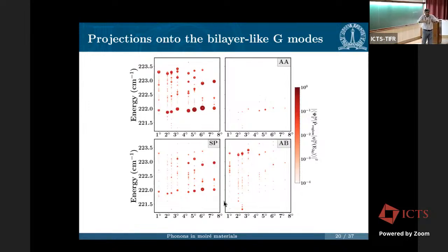So we think that the reason why this is splitting is indeed because of this very simple reason, that as your angle becomes smaller, these regions become larger, the AB and BA regions become larger and dominate your Raman spectra. Whereas when the angle was larger, these regions are all almost equal in area, and as a result you measure an average quantity, and that is the reason why this thing goes up and then starts going down.